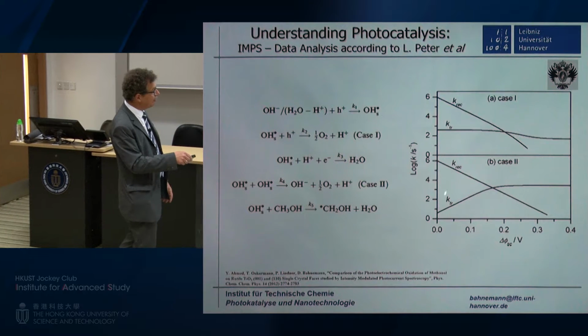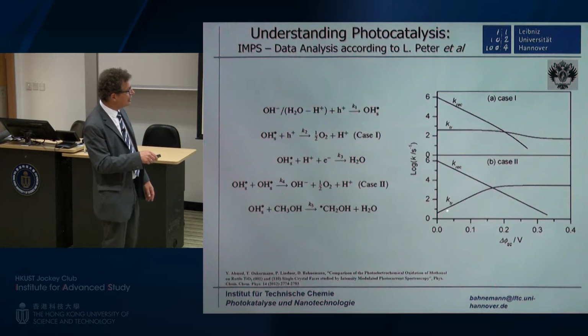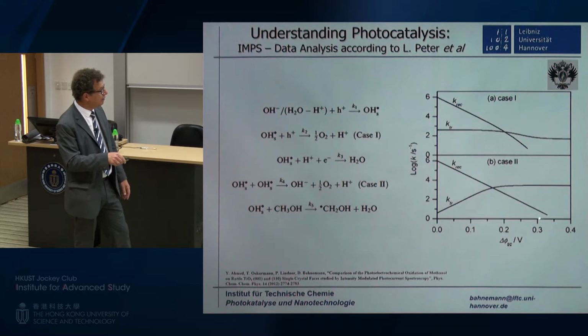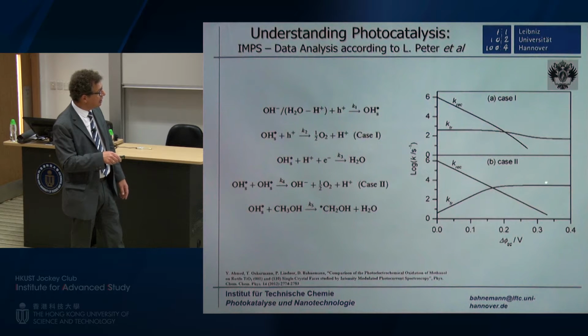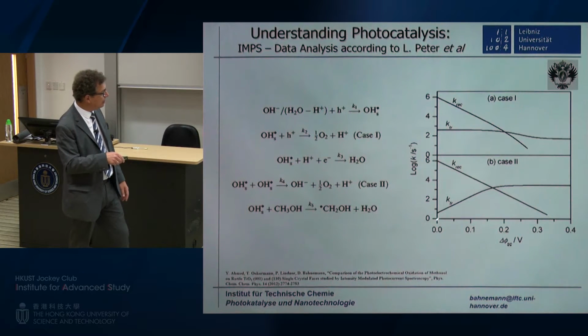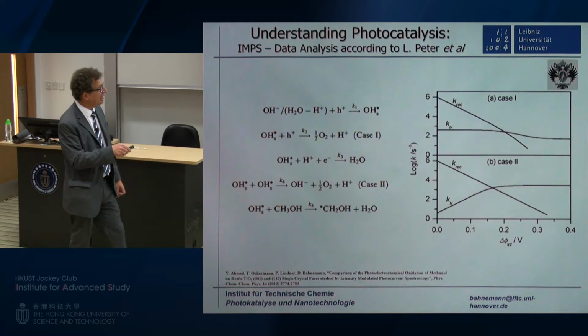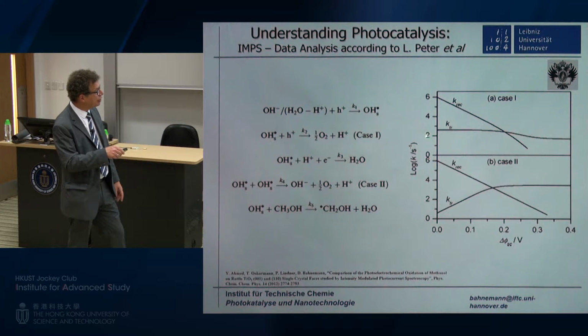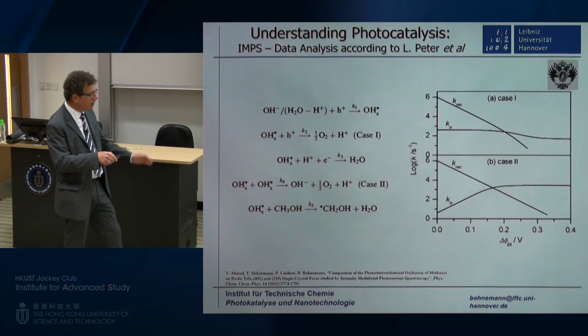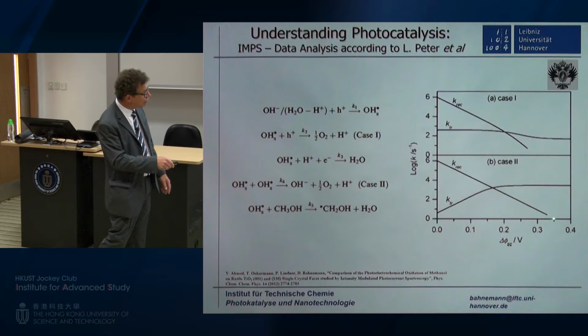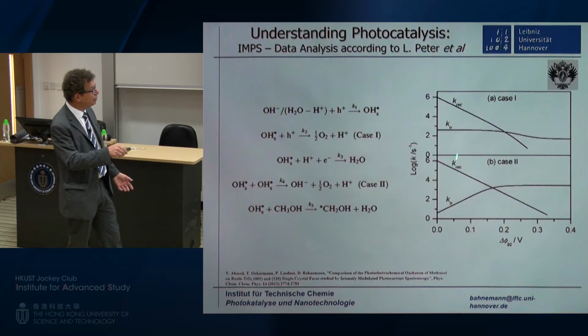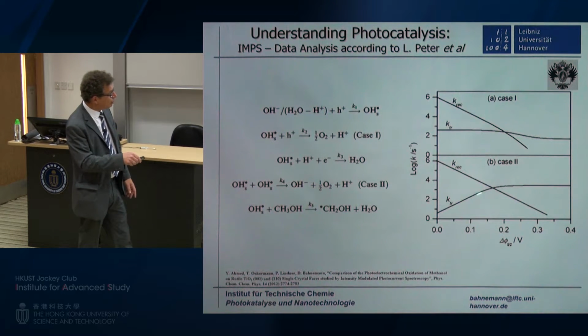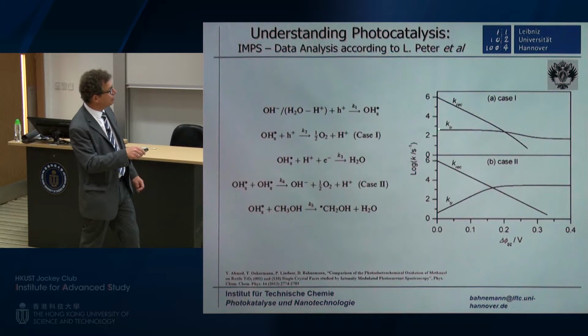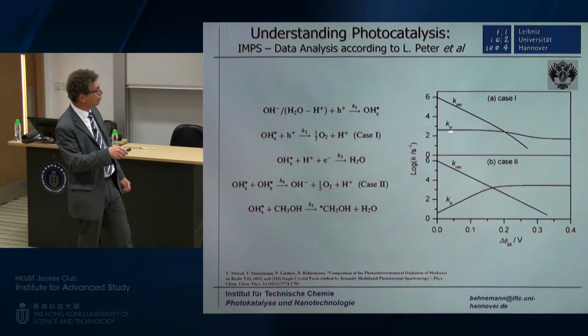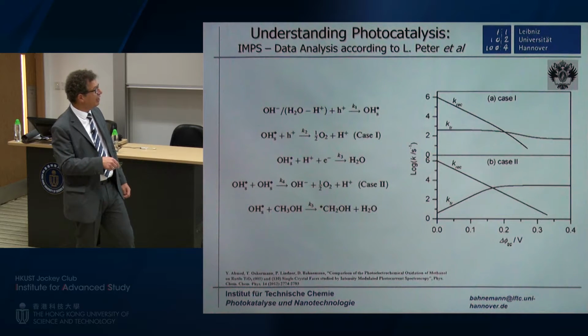And the interesting thing is, if you do your calculations and you look at the rate constant for electron-hole recombination and for the trapping of the holes, both of which you can get experimentally, the theoretical predictions are that in both cases, as you increase the voltage in the system, the recombination rate constant decreases. So this cannot be used to discriminate between these two cases. But the trapping rate constant increases here with increasing potential, and it decreases here or stays almost constant as a function of the potential.